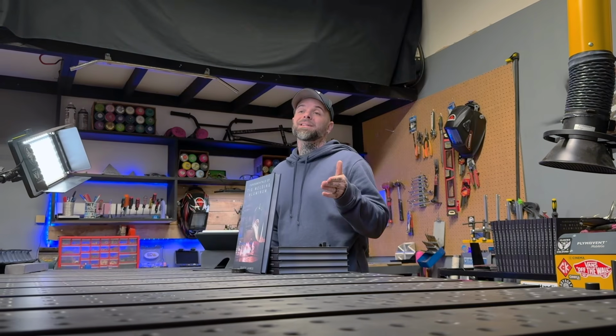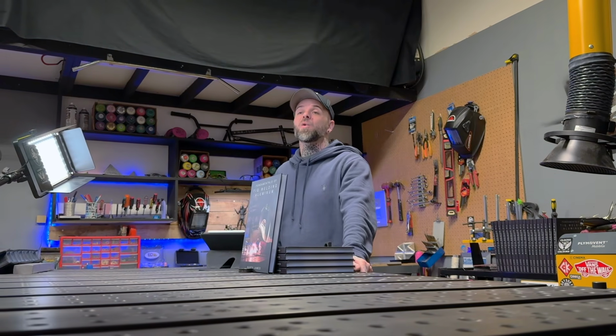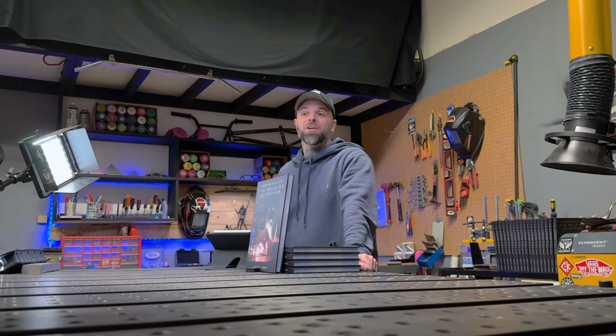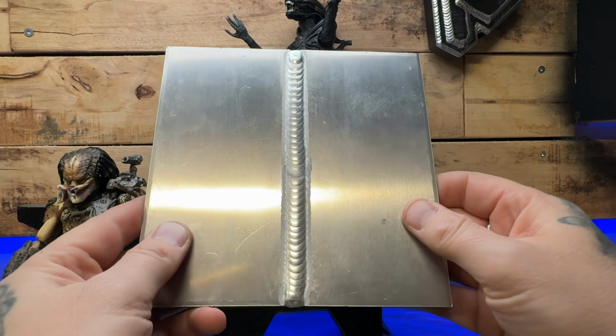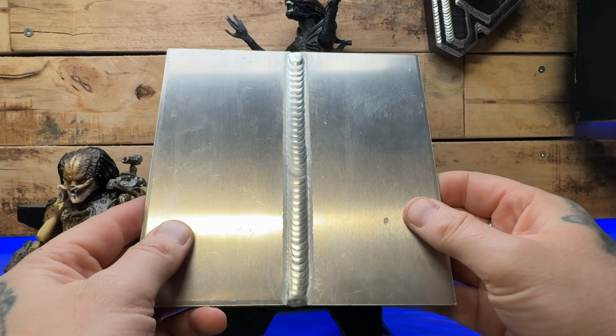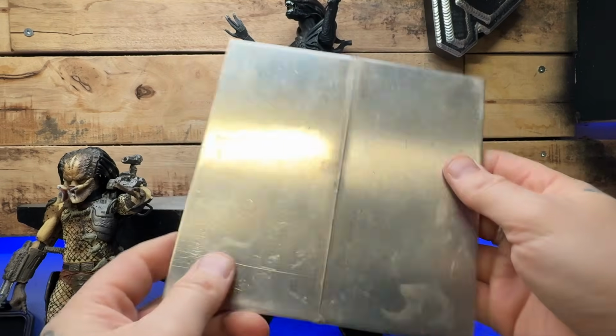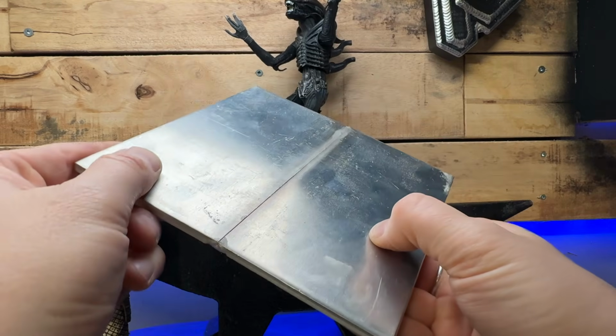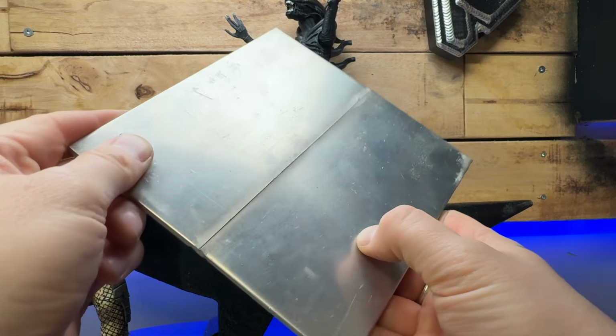And there are even welding tests with thicker joints like I show here using a butt joint configuration. Again, this is actually welding over the butt joint configuration with 1/4 inch material. Again, looking at the backside, surprise, surprise, we don't see any penetration. Oh my gosh, let's not freak out.